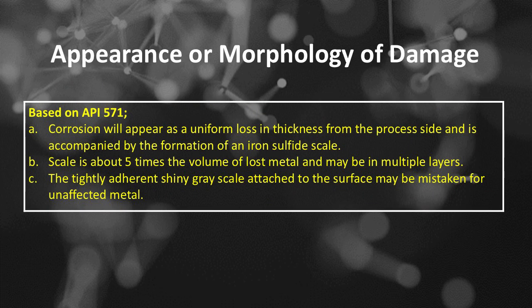High-temperature hydrogen (H2) and hydrogen sulfide (H2S) corrosion appearance or morphology of damage based on API 571. Number A: Corrosion will appear as a uniform loss in thickness from the process side and is accompanied by the formation of an iron sulfide scale. Number B: Scale is about 5 times the volume of lost metal and may be in multiple layers. Number C: The tightly adherent shiny gray scale attached to the surface may be mistaken for unaffected metal.